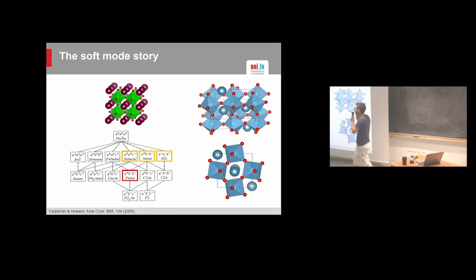So, tilts in perovskites. This is the cubic perovskite, like barium zirconate that I was talking about. I am not talking about ferroelectricity. I'm only talking about the tilts of the octahedra, so I'm talking about ferroelasticity. There is a tilt angle, there is a strain, but there is no polarization. Now, there are many ways that you can tilt these octahedra together, and of course this has been studied for a while, so we know exactly what kind of tilt leads to what symmetry.